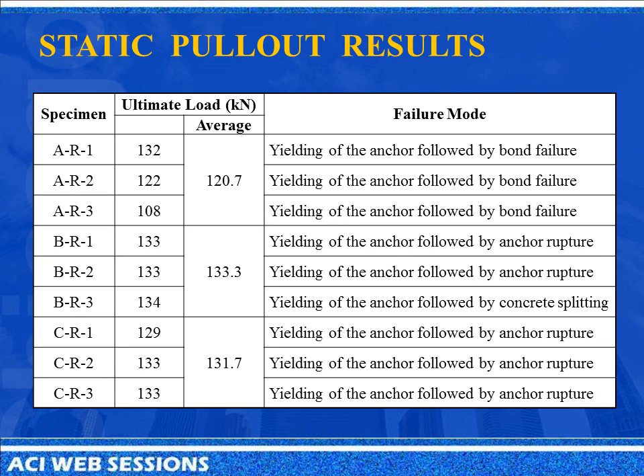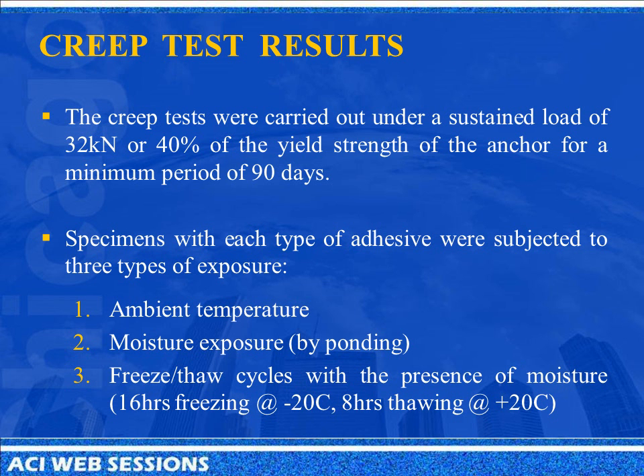This table summarizes the static test results that we got. So as you can see, for type A, the ultimate load was about 121 kilonewtons, versus for type B and C, the epoxy-based ones, about 132 to 133 kilonewtons. And type A all failed by bond, while types B and C failed by anchor rupture. For our creep test results, like I said, the sustained load level that we used was 40% of the anchor yield strength. Creep test lasted for a minimum period of 90 days.